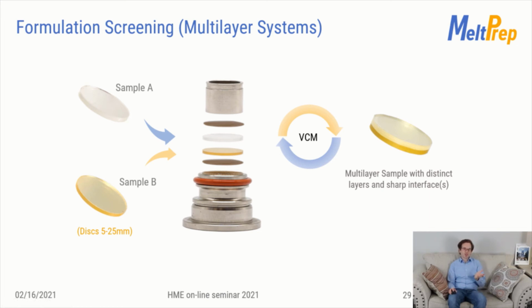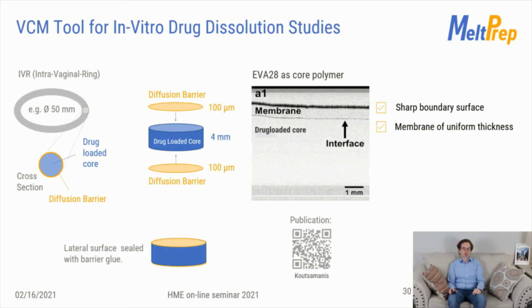One application for multi-layer systems are similar systems to the contraceptive intravaginal ring that you may have heard of, the NuvaRing. A group in Graz wanted to study such a structure and try to mimic the complex structure of the NuvaRing. The NuvaRing uses a drug-loaded core with a surrounding diffusion barrier. So you have a core and the surrounding diffusion barrier, and this limits the drug release.